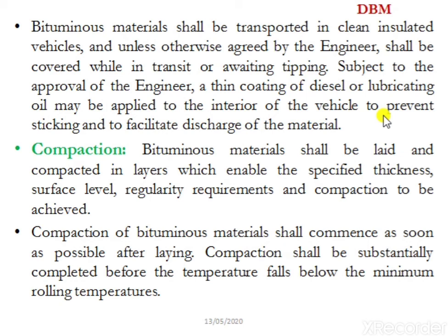The minimum temperature for the mix at the time of laying shall be between 140 degrees Celsius and 160 degrees Celsius. After laying, the bituminous mix is compacted. As soon as the mix has been laid by the paver, compaction shall be done with the help of a set of rollers moving at a speed not exceeding 5 km per hour, following close to the paver. The roller sequence will be as under, or as established during laying trial stretches.